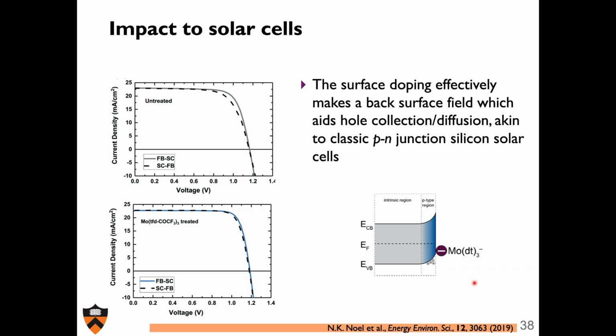Nevertheless, you can make a really close analogy with a type of early silicon solar cell, the screen-printed aluminum BSF, back surface field solar cell. The back here is basically p-doped, and it does promote hole collection. So devices are actually aided by putting a little p-doped back surface on an NIP type structure. It's not necessarily a bad thing, but it doesn't really get to the core of true doping.